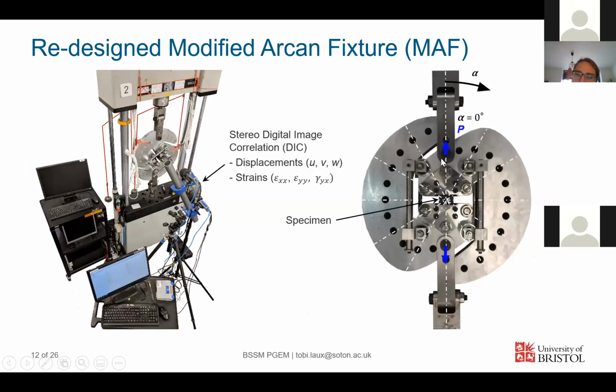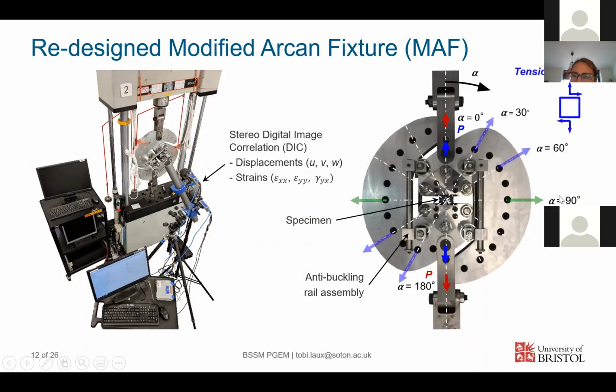So if you follow the blue arrows, if you use these two holes, then you tension the specimen. If you use the holes hidden away here, then you compress the specimen. If you pull here, you shear the specimen. And if you're in between those places, then you have tension shear in the specimen, and here compression shear. So the loading angle here is denoted alpha. We would have at 0 tension, 90 shear, 180 compression. That's just definition. And during this experiment, what we used is digital image correlation on the specimen, so we could obtain the displacements and the full field strains.